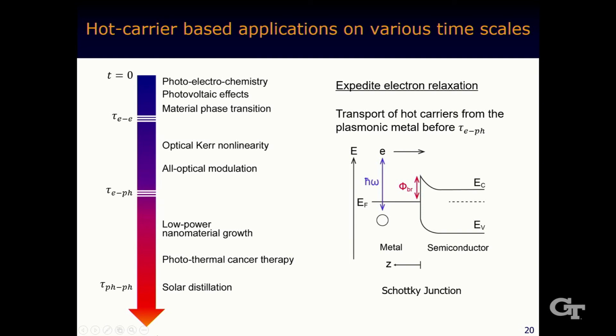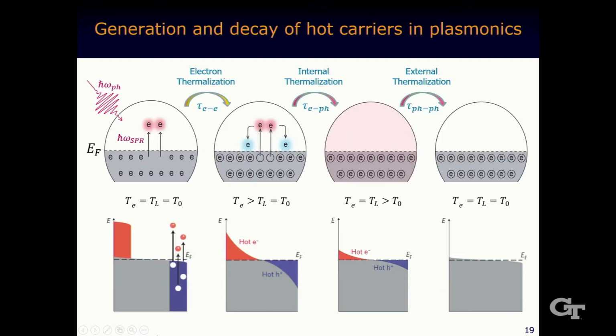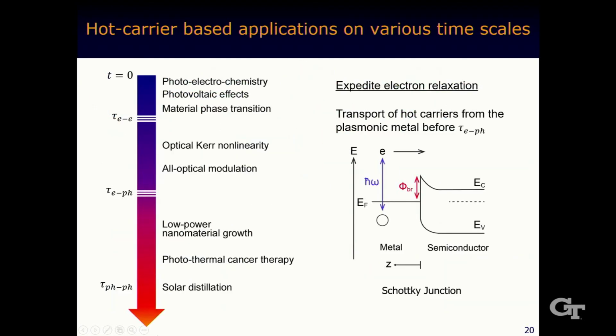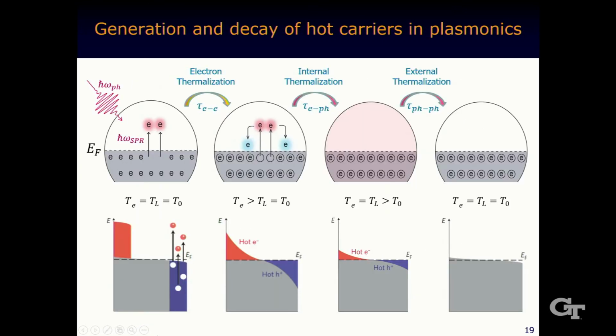Depending on your application, for example, in many applications in photochemistry, we need to make use of the energetic electrons immediately after the Landau damping, even before a well-defined hot electron is produced. And on the other hand, for many heat-related applications, the temporal response is not important at all. And for all-optical modulation of the metallic property, the response itself can be relatively slow because, as I said, it takes a picosecond or even longer for electrons to reach equilibrium with phonons through electron-phonon scattering.